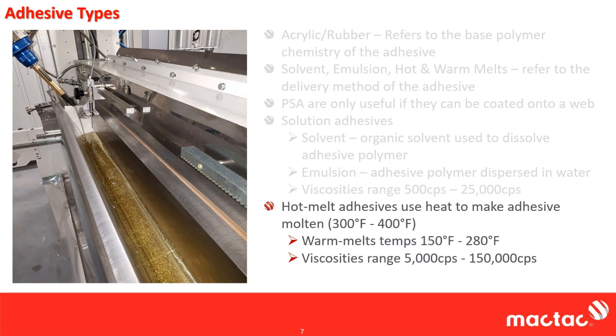The viscosities of hot melt and warm melt adhesives are quite a bit higher than that of solution adhesives. On the low end, you get maybe 5,000 centipoise. On the high end, you're going to top out at about 150,000 centipoise. So again, 150,000 times thicker than what water would be.